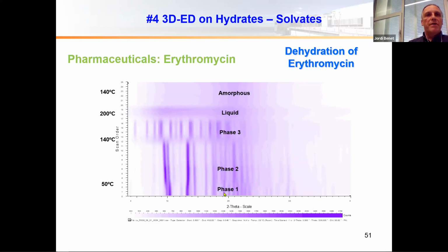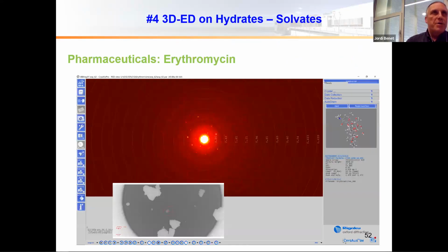So we measured phase 1, phase 2, phase 3, doing powder diffraction with variable temperature until it melted, and then we saw it didn't recrystallize. But what we were interested in was to see how many crystalline phases. And so we focused on obtaining phase 1 of this sample of this antibiotic, which is called erythromycin, in our 3D-ED system. And we did a quick experiment.